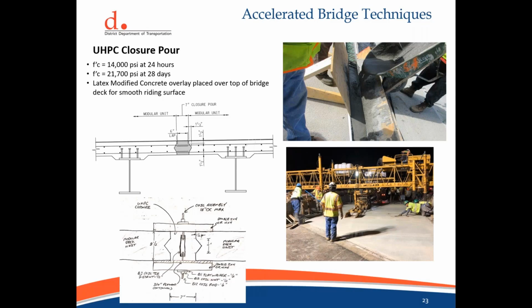Originally, we had proposed a 3/4 inch PPC or polyester polymer concrete overlay to create a uniform riding surface. The contractor ultimately proposed a 1 1/4 inch latex modified concrete overlay. LMC is about half of the cost of PPC, and the contractor was a bit more familiar with this type of installation, so this was ultimately approved by DDOT.